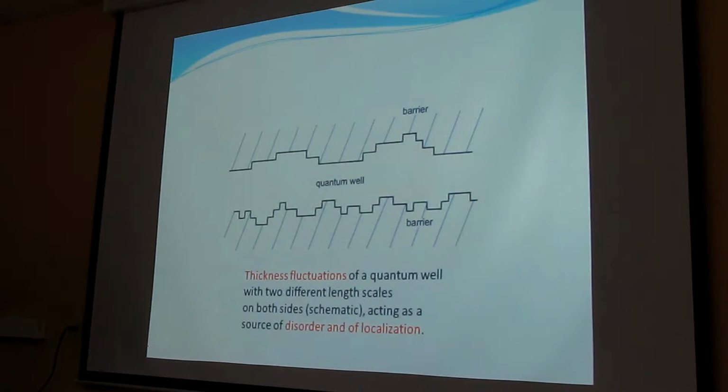One important aspect for quantum wells is that you always have a certain amount of disorder. For example, if you grow a barrier of aluminium gallium arsenide, then a gallium arsenide well and another barrier, you cannot avoid fluctuations of the well width of at least one atomic layer, frequently more. And then you get localization, so maybe you localize a hole here or a hole here, and you can bind the electron to it, so you usually get localized states in quantum wells.